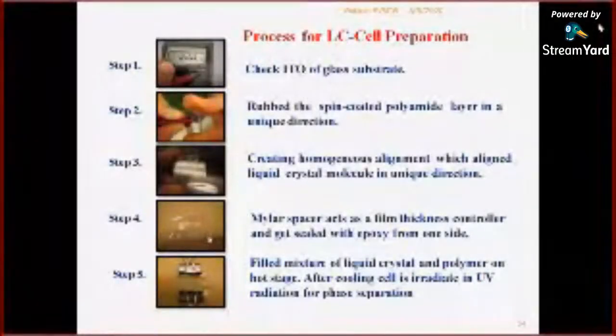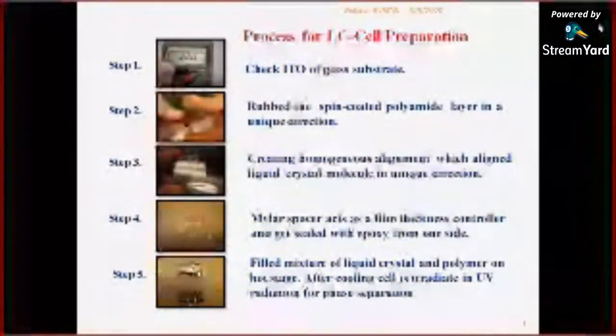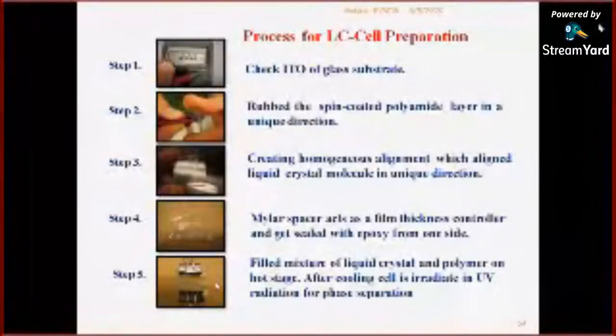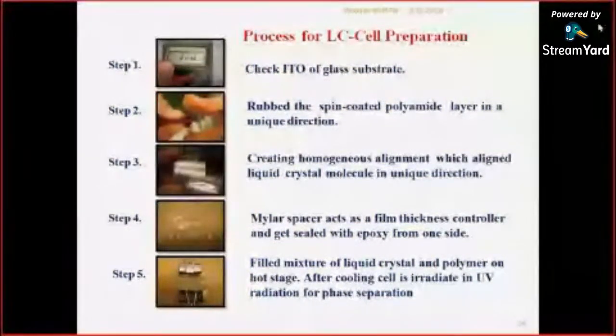After achieving the alignment on that substrate, we fill the samples, and here some spacer is there. We put the spacer on this substrate, and further we put another substrate on this sample, and we clamp the cell. This forms a capacitor-like structure, and we put the sample here. That sample has flow-like properties. So the sample gets filled in this substrate, in these liquid crystal cells, by heating it.